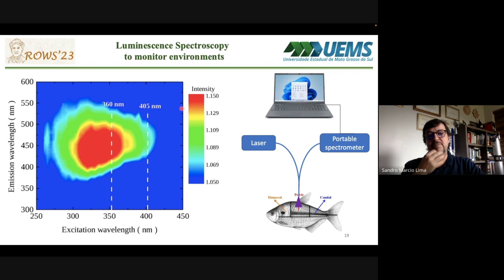Due to the broad excitation region, which could be indicative of different agents responsible for the fluorescence signal, the experiments were performed using the UVA excitation at 360 nanometers, and the blue excitation at 405 nanometers, which was chosen because it is very easy to be purchased, and some diode laser models in this wavelength are very cheap. So experiments were performed in these two excitations, and the photoluminescence was captured by the bifurcated optical fiber until the portable spectrometer, so that this apparatus is